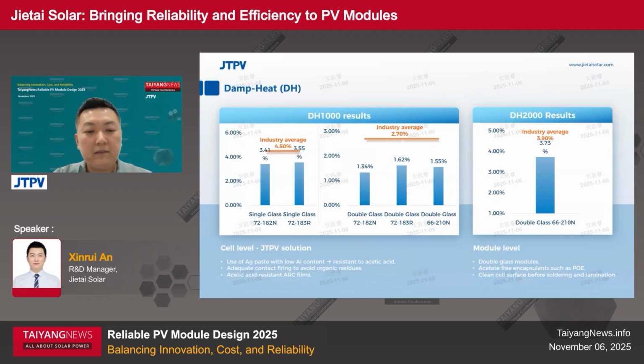So in JTPV, on the cell level, we think that the most effective way to mitigate DH degradation is by tuning the composition of the silver paste. We put continuous efforts in reducing the aluminum content and any other components easy to react with acetic acid. We also align our firing conditions recipe to the organic system of the silver paste to avoid any residuals after firing that might be reactive under DH conditions. And finally, also make sure that the anti-reflection coating layer is free of blistering and therefore resistant to acetic acid.